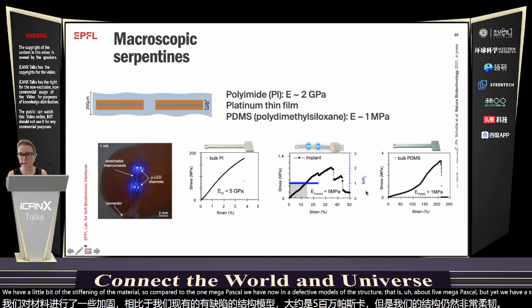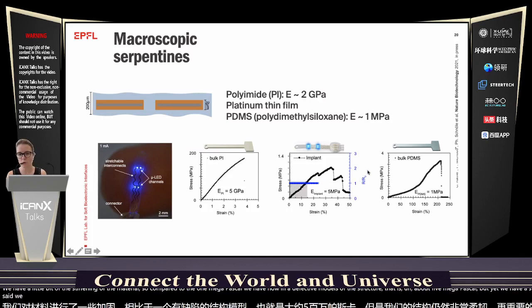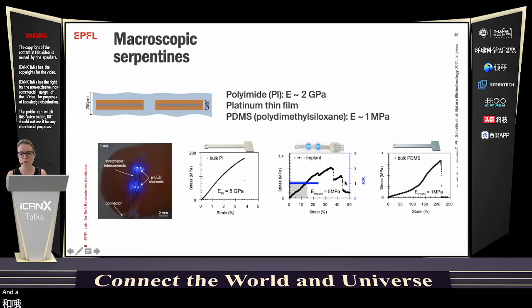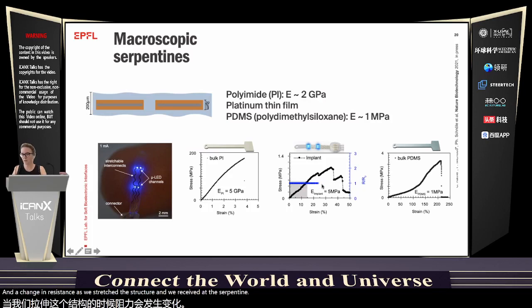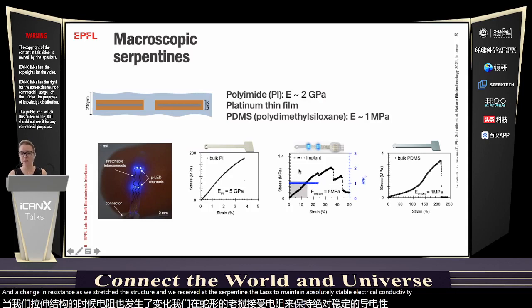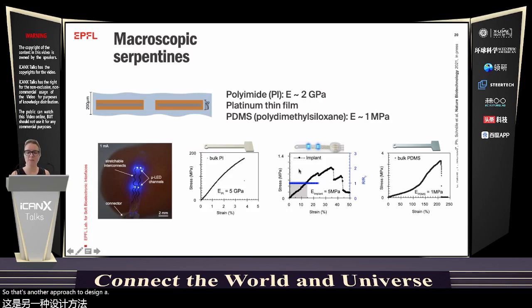And more importantly, we monitor a change in resistance as we stretch the structure, and we see that the serpentine allows us to maintain absolutely stable electrical conductivity. So that's another approach to design our stretchable structure.